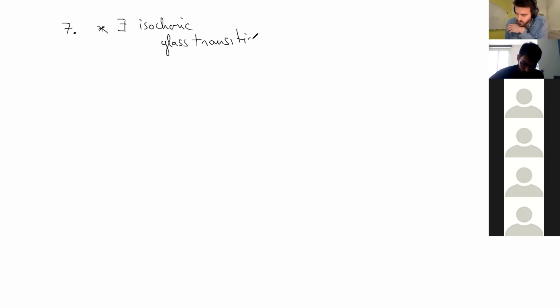So you have systems where the pressure is not maintained, but the volume is maintained. And so, of course, there you won't see any vanishing of free volume, right? The volume is constant. So all the argument about the free volume is completely wrong for those systems. But then people argue that, in that case, you replace the volume by the pressure, the coupled quantity, and redo the argument with pressure, and then you would have a proper glass transition. Anyway, it has been criticized.